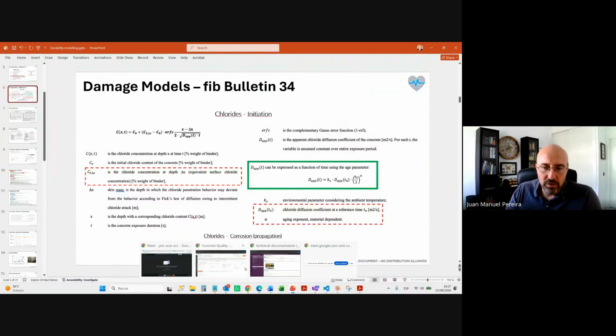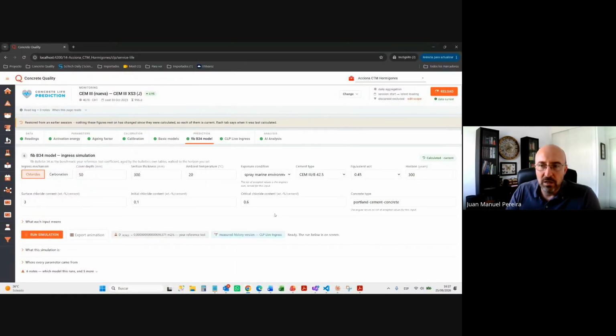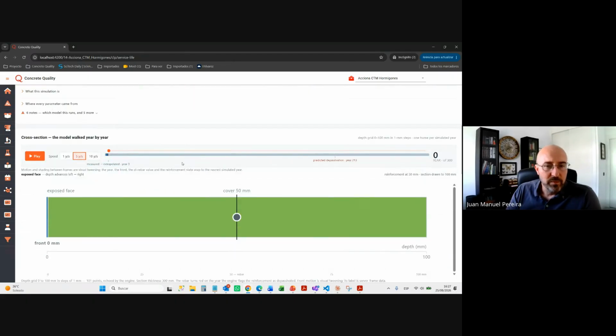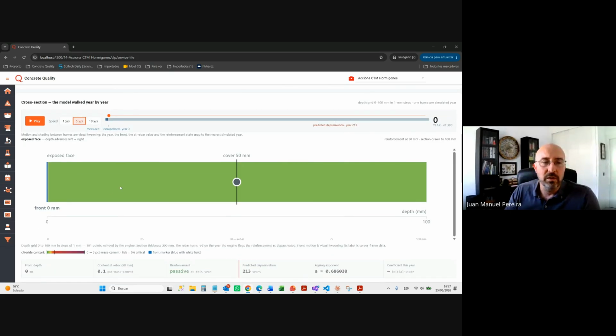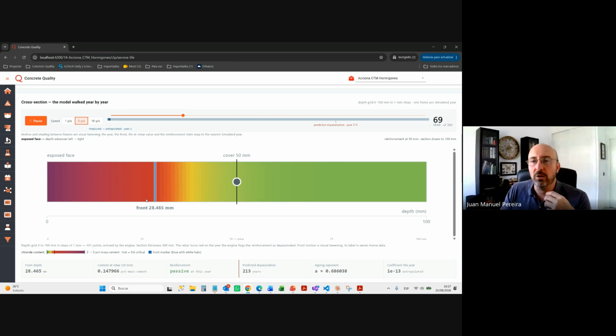And this shows in the software like this. We have all the configuration here. So if this is a concrete, and this is green because it's the initial concentration of chlorides, and this is the rebar. So if we play, we can make an animation of what happens over time, and you see how the chlorides will be more and more concentrated over time, how the concentration is distributed, how this front, which is the critical concentration for the corrosion to start, will move over time. And when it reaches this rebar, it will turn from passive to depassivated.